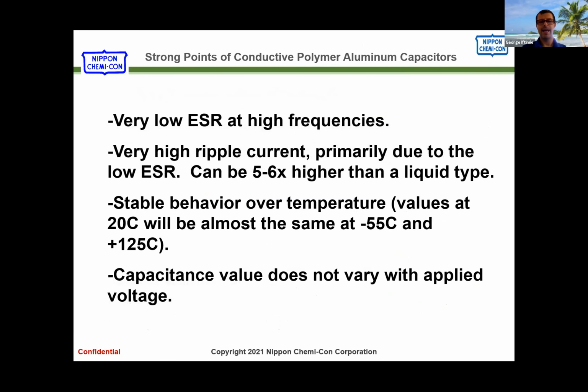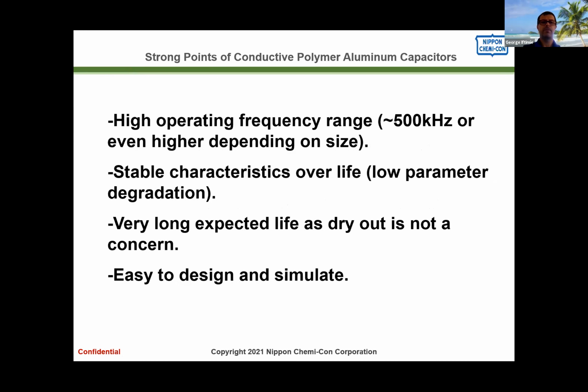Most of the advantages are due to its solid electrolyte. It stays solid, so it has a very low ESR, especially at high frequencies. It has a very high ripple current, primarily because of the low ESR. It has an essentially flat behavior over temperatures. So when you're designing with a capacitor, whatever you see at room temperature, you will see at -55 or at +125 degrees Celsius. Same as electrolytic, capacitance doesn't change with the applied voltage in any way. Operating frequency range is wide. It has a very low ESR, so for the most part a very high resonant frequency. It's not uncommon to see them operate well over 500 kilohertz or even megahertz, especially on the small size parts.